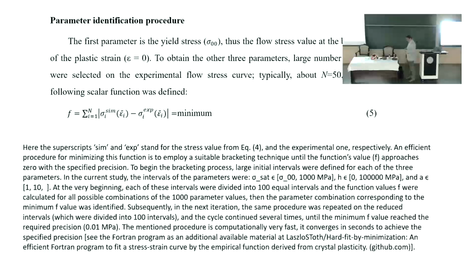So we have experimental data, a number of points from i to n, number of experimental points. And we want our function to approach those points the best. So you have these experimental values of the stress at different strain values, and then by taking some initial parameters, you will get the simulated one from the function you established, and then you just look at the difference, absolute value. It should be minimum, and it's approaching the best. So this is just a function we are trying to minimize.